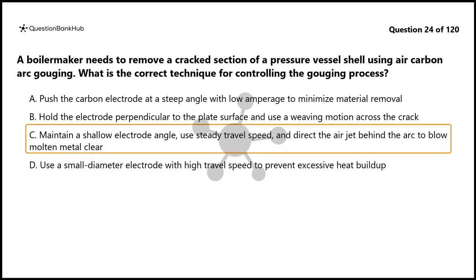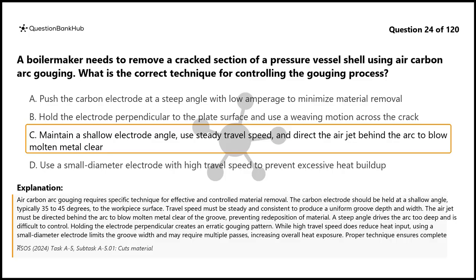The correct answer is C. Air carbon arc gouging requires specific technique for effective and controlled material removal. The carbon electrode should be held at a shallow angle, typically 35 to 45 degrees, to the workpiece surface. Travel speed must be steady and consistent to produce a uniform groove depth and width. The air jet must be directed behind the arc to blow molten metal clear of the groove, preventing redeposition of material. A steep angle drives the arc too deep and is difficult to control.